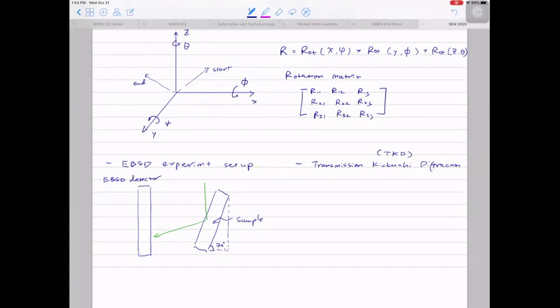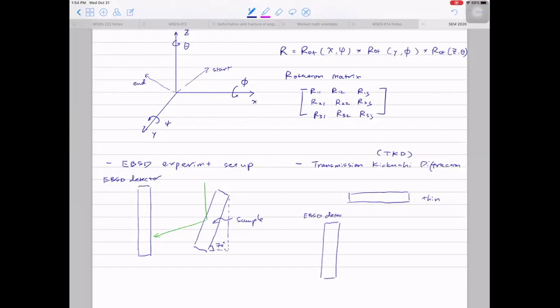The principle of TKD is simple — very similar to EBSD. But instead of tilting the sample by 70 degrees, the sample is flat. However, the sample must be very thin — usually around 100 nanometers in thickness. You position the sample above the EBSD detector, and instead of using backscattered electrons, you use forward scattered electrons to form the diffraction pattern.